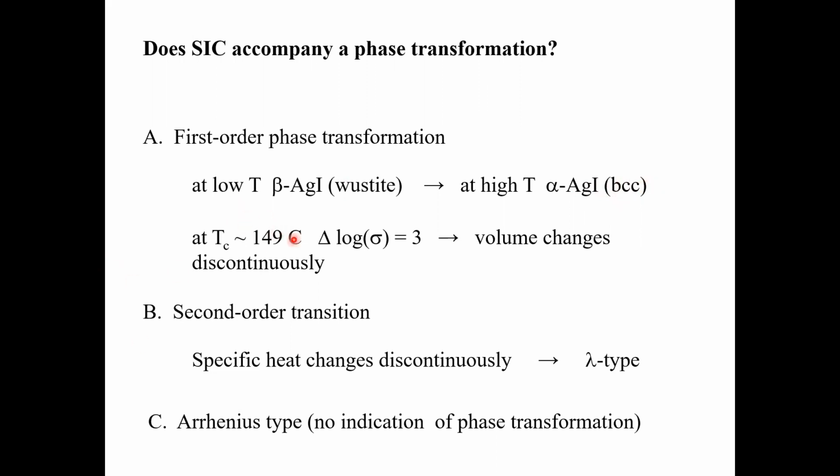And this transition temperature is around 149 or 150 degrees. Around that transition temperature, if we look at the logarithm of conductivity, there are 3 orders of magnitude change and an associated volume change, a first order transition.